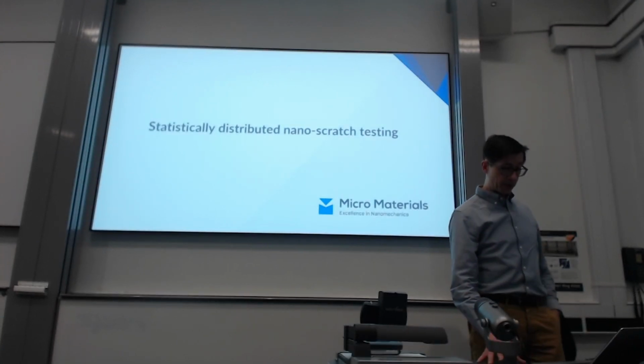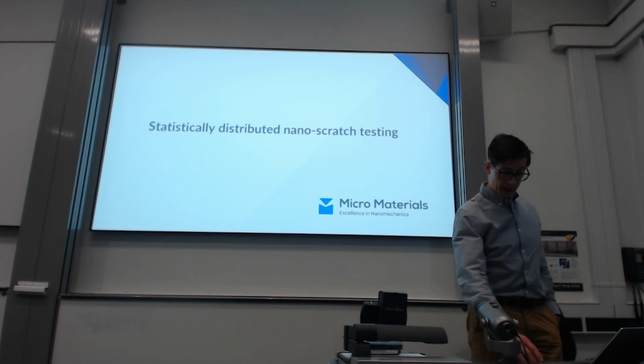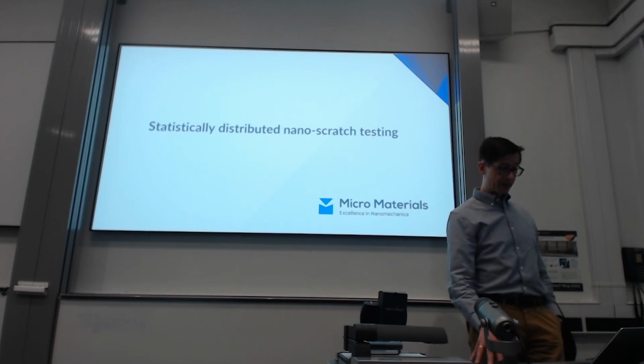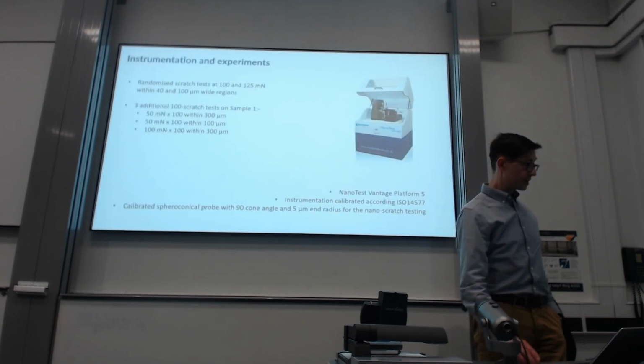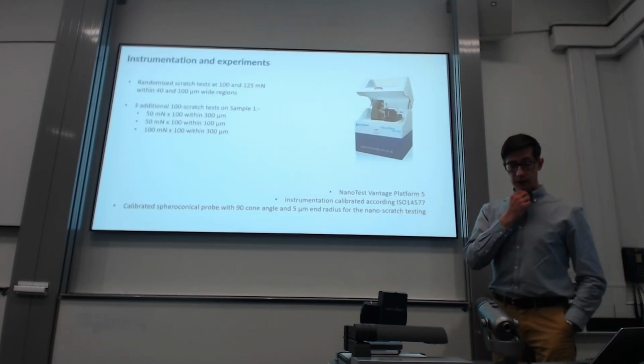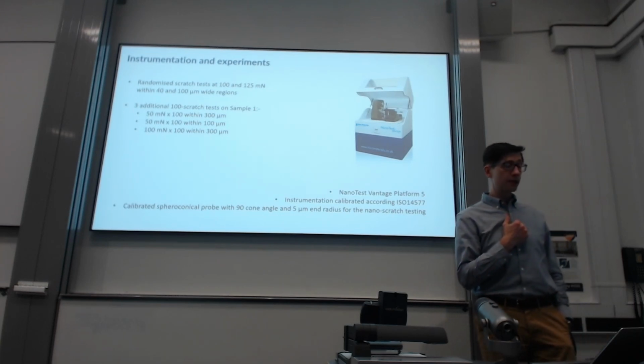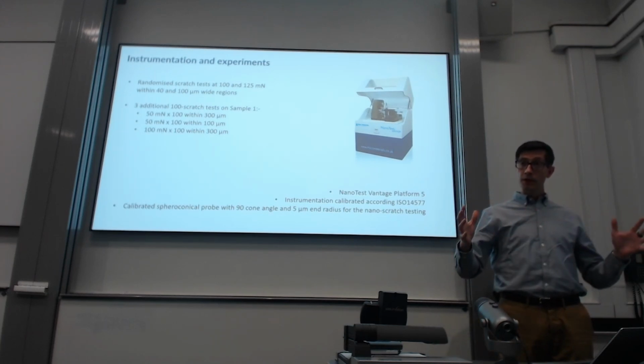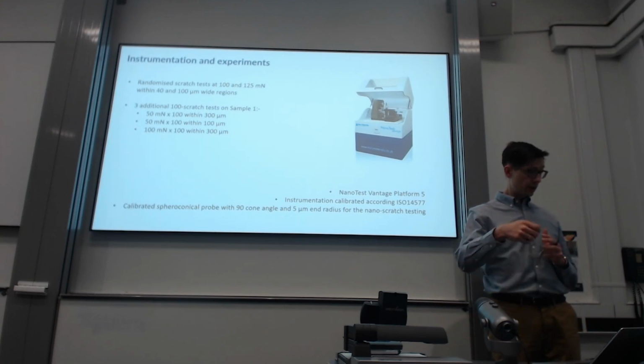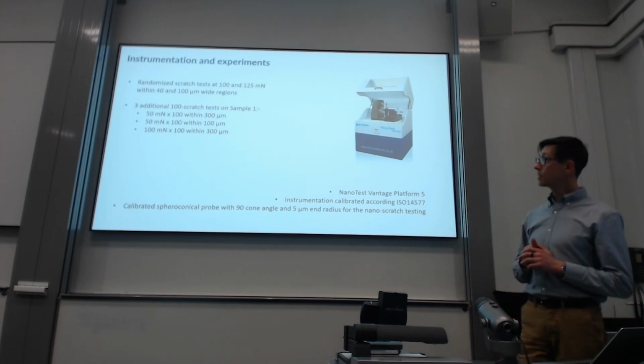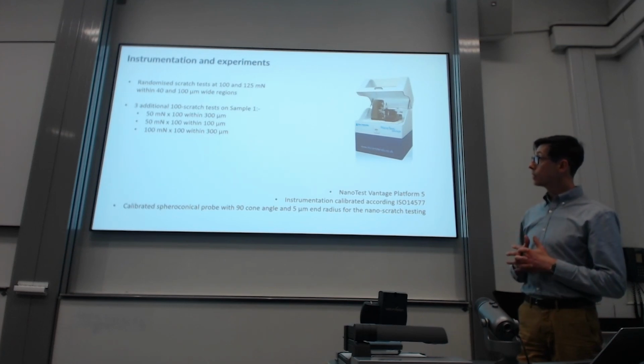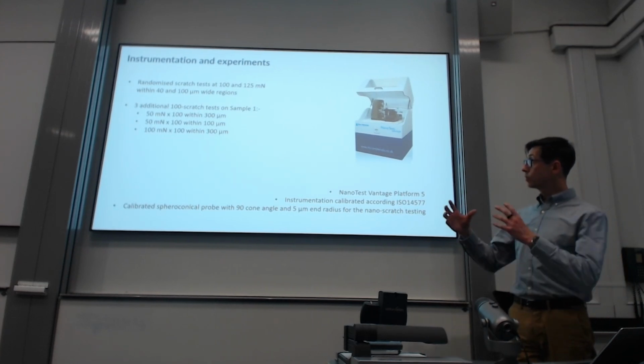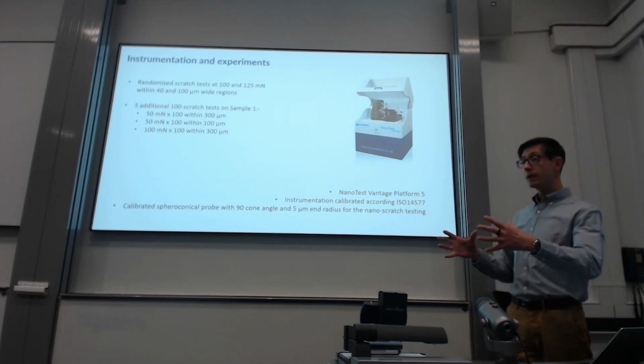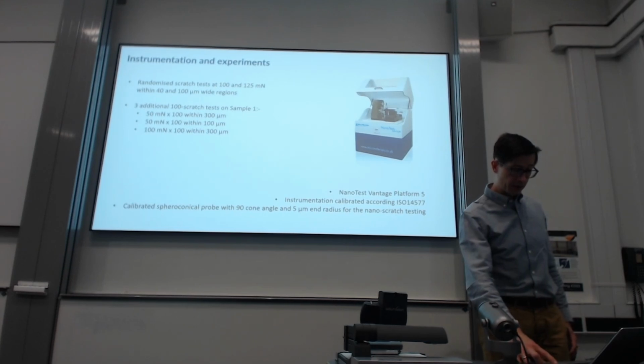So in the second part of mechanical characterization, we looked at a relatively novel method proposed by Micromaterials, which is statistically distributed nano scratching testing. Here we decided to run randomized scratch tests at 100 and 125 millinewtons with 40 and 100 wide regions in terms of spread of those scratch tests. And then we decided to look specifically at sample 1 and perform some additional 100 scratch tests on that sample with varied loads and varied area, and you will see why we decided to do that.